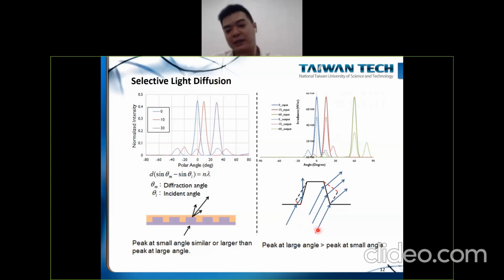It is that for this type of structure, in order for large angle light to be refracted back to the smaller angle, you need to encounter this total internal reflection. If you encounter this side, it will be diffused to a larger angle. So only if you encounter this sidewall here with total internal reflection, it will be reflected back to the smaller angle. So you can see that the diffusion peak at large angle will be larger than the peak at the smaller angle. This is what we call the selective light diffusion.